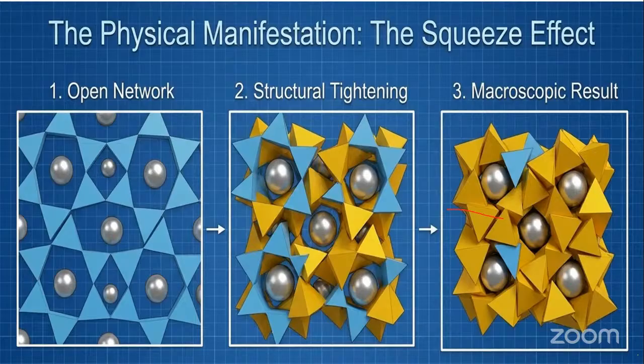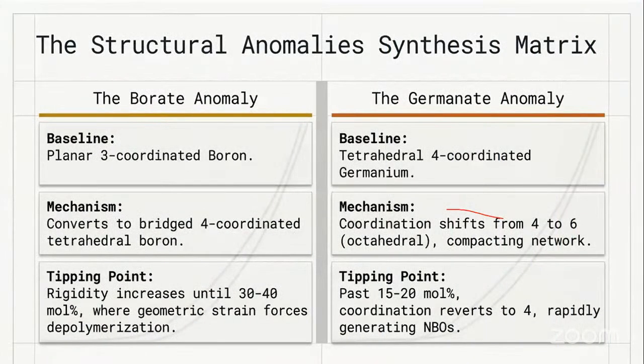So once the anomaly appears, it leads to formation of non-bridging oxygens. Normally, what this anomaly does, say for example borate and germanates, both these are the two premier glass formers. They exhibit anomalous behavior. With respect to boron, you see three coordinated planar structures, whereas in germanium it is four coordinated tetrahedral structures.